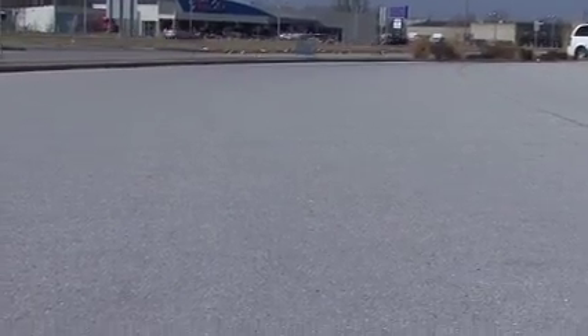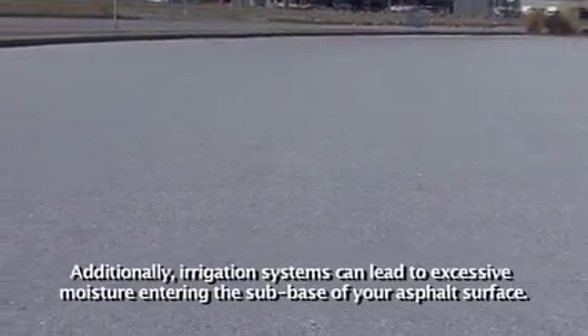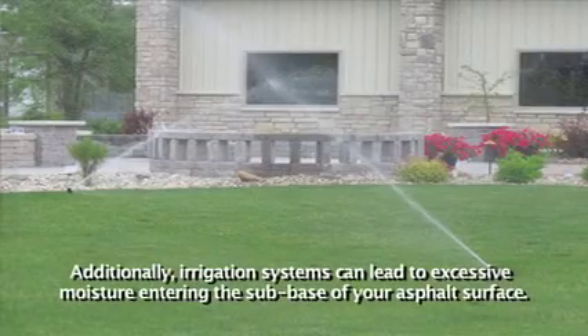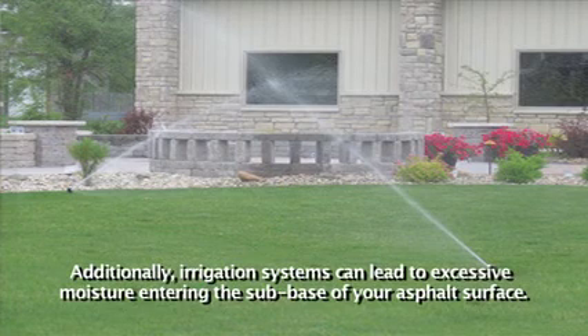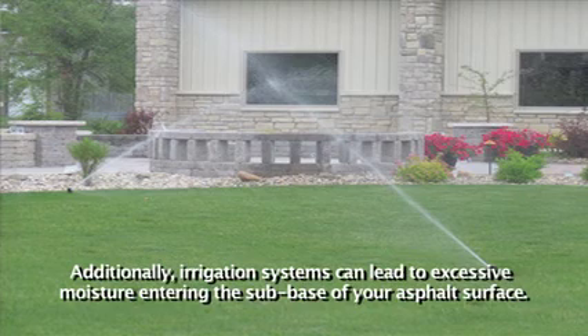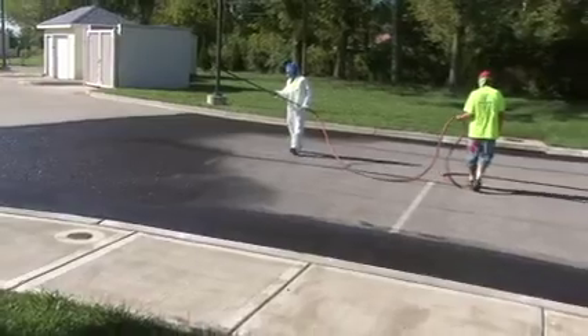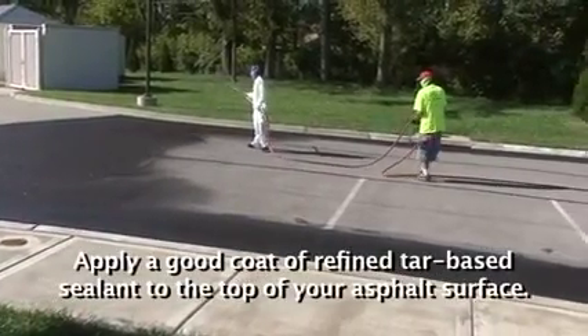And water, whether rain or irrigation systems, is an issue. We face a lot of issues with irrigation. I think some people just think of rain, but on these commercial lots, the irrigation system is running twice a day on a lot of them, from late March up until November sometimes. If water is able to get through that asphalt into the subbase, it's going to keep the subbase soft, again causing failure. So we try to educate the customer that once you've done the crack sealing, it's recommended that you put a very good seal coat on top of the surface.